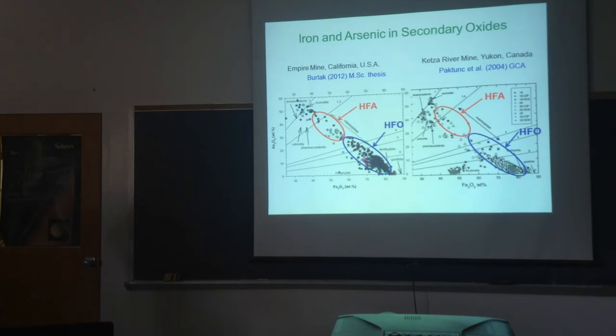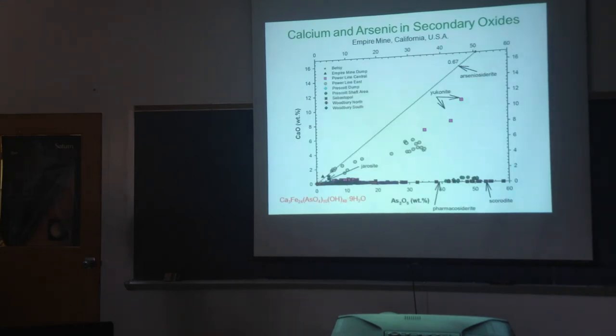And then if we compare this to a previous study done in Canada by Paktunc at a place called the Ketza River mine, you see a pretty similar distribution. There's some minor differences. He had a little more of the yukonite, pharmacosiderite, or sarmientite, these calcium-bearing minerals. He had more of those than we did here at Empire Mine. But we had a little bit of scorodite and a lot of this HFO, HFA. Another plot that Paktunc looked at that's instructive is arsenic versus calcium. Again, microprobe data. In our data from Empire Mine, we had a lot of data with very little calcium, but a few samples had the high calcium. And again, we're interested in that because it was known that the high calcium minerals were the ones that are most bioavailable.